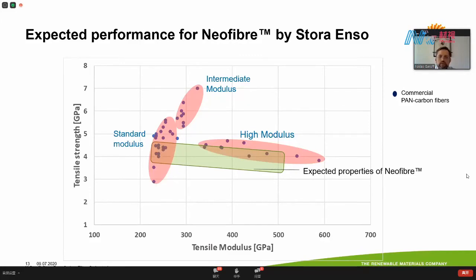And this corresponds to about 70% of all carbon fibers being in this standard modulus regime. These are the carbon fibers that are being used for industrial applications such as rotor blades, automotive, construction. Then we have another group called intermediate modulus fibers. These have much higher tensile strength and somewhat higher modulus. This is the high-priced carbon fiber that is used for primary structures in aerospace, in airplanes, such as wings.